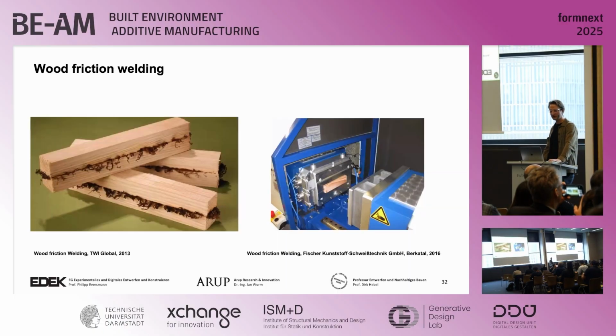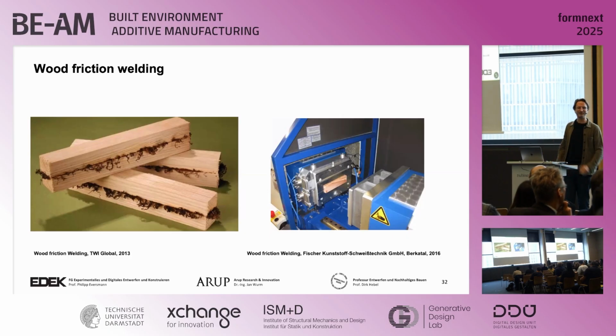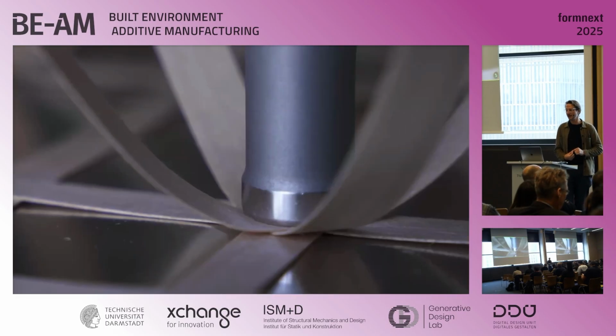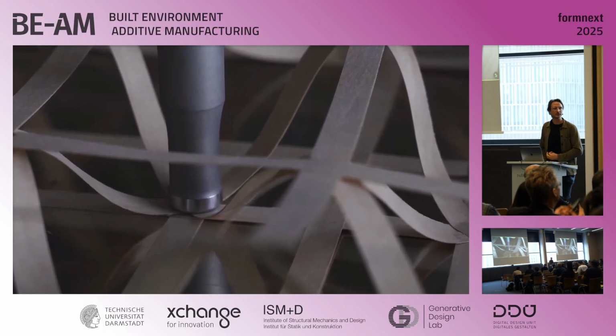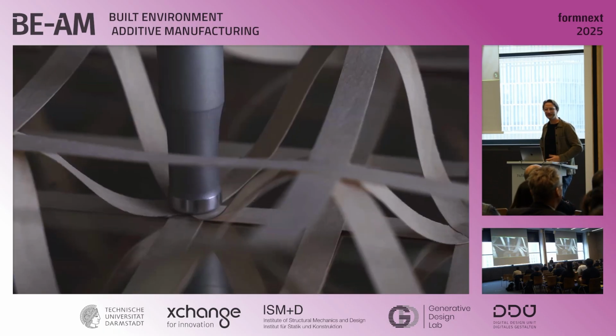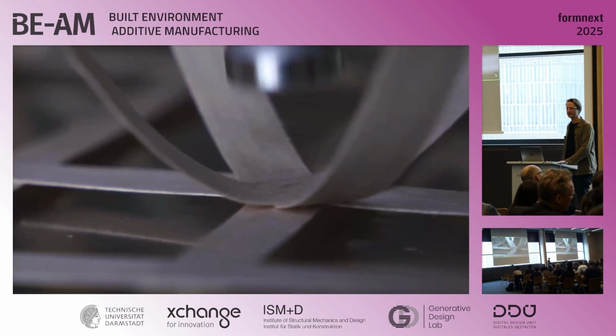And for that, we also explored a different kind of joining where we wouldn't use any adhesives anymore, because if you go more into these biomaterials, at some point you say you really want a 100% bio-based product. And so we looked at, at the time when I was visiting research professor at EPF Lausanne, there was friction welding studied there, huge machines and so on, where you use thermal energy, putting together timber by only rubbing it together, and you can activate the lignin in the wood, creating a natural bond. Since we are using these paper-thin elements, we don't need so much energy, so we went into another process, which is called ultrasonic welding. And you know this from the masks we were all wearing a couple of years ago. Those are actually done through ultrasonic welding, so it's more in the plastics industry.